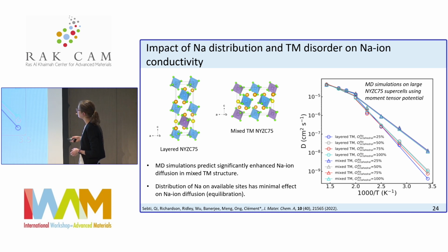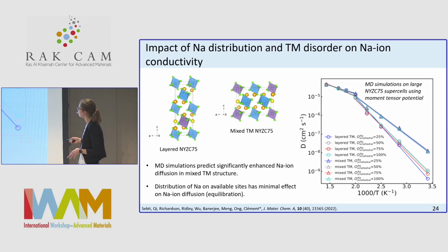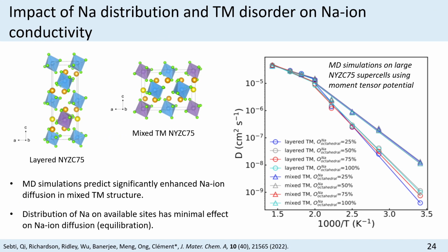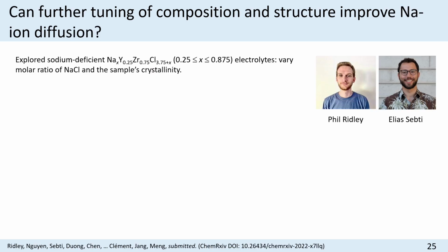And we also looked at different ways of distributing sodium over octahedral and prismatic sites. So here I'm showing you the percentage of octahedral site occupation. Basically what you're seeing is that the circles here are for the layered model. All of them have a lower diffusion coefficient for sodium compared to the mixed system, whereas the distribution of sodium on prismatic and octahedral site doesn't matter very much. So what that's telling you is that mixing transition metals in these materials will improve sodium transport.